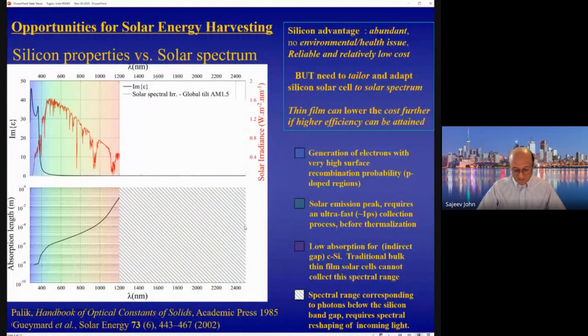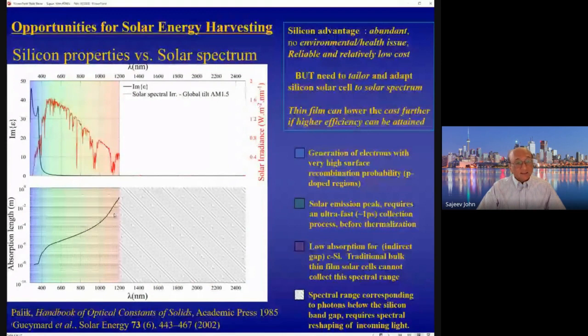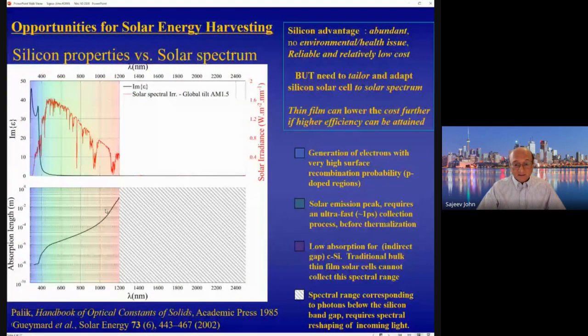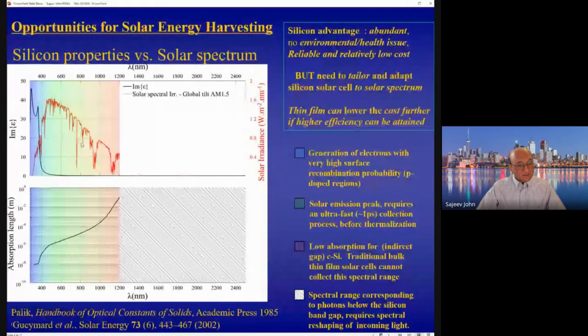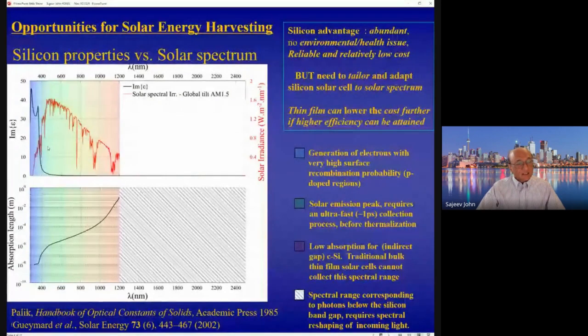Now, silicon has a great deal of difficulty in absorbing that sunlight because it is an indirect band gap semiconductor. So here, what I've plotted in red is the spectrum of the sun as it's seen on the surface of the Earth. It looks like a black body spectrum at around 5,700 degrees, except for these dips associated with certain absorptions taking place in the atmosphere. And next to that, I've plotted the imaginary part of the dielectric constant of silicon, which is what enables it to absorb.